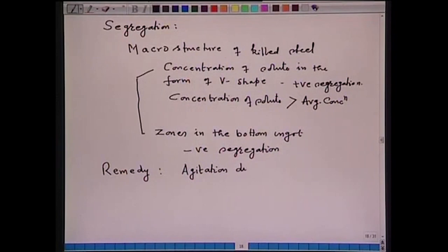Agitation during solidification. Now, we have to see how we are going to provide agitation during solidification, because if you can agitate the liquid steel during solidification, then it will homogenize the concentration, and hence chances of segregation will be minimized.